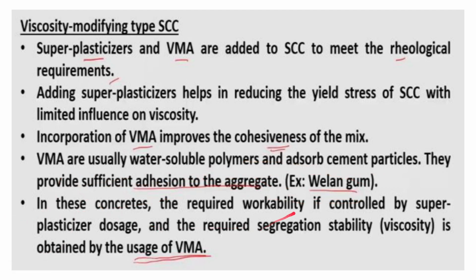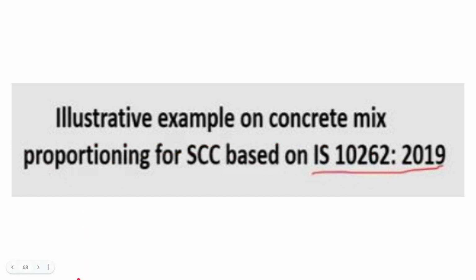In these concretes, the required workability is controlled by the superplasticizer dosage, and the required segregation stability, that is viscosity, is obtained by the use of VMA. So as we discussed initially also, workability is controlled by superplasticizer dosage and viscosity is controlled by VMA. So both have to be mixed in appropriate proportions. Now let us go to an illustrative example, where we can see how the mix design of self-compacting concrete is done, based on IS 10262 2019. Let us see that.